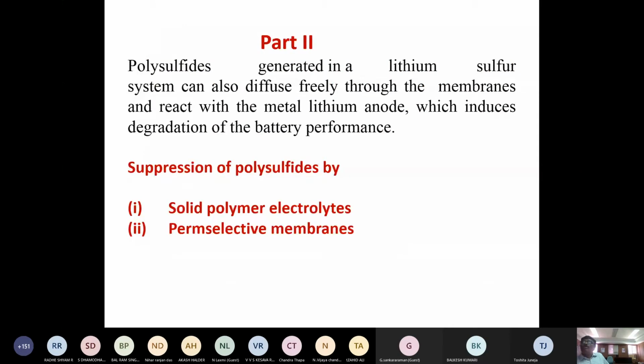But now we focused on the second part. How can we suppress the shuttling of the polysulfides? Because the shuttling is a very serious issue which prevents this system from commercialization and also eventually leads to self-discharge. The polysulfide shuttling can be suppressed in 2 ways. One is, instead of the non-aqueous liquid electrolyte, you can introduce a solid polymer electrolyte, or you can introduce a perm selective membrane which can capture the polysulfides and allow only the lithium ions. So these are the 2 ways that can be employed.